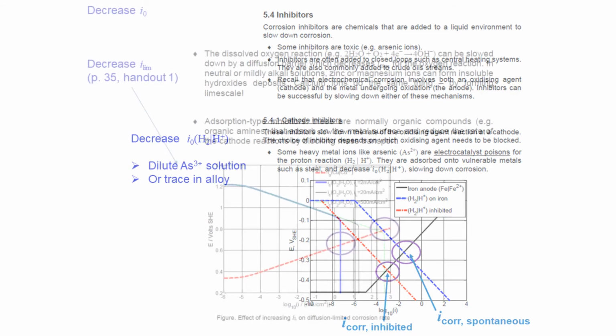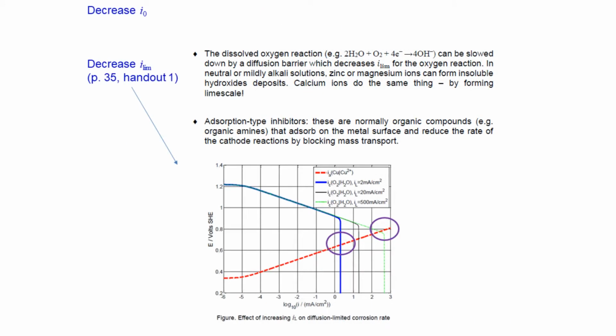We have a different kind of inhibitor to consider if our oxidizing agent is dissolved oxygen. This is because dissolved oxygen very often causes corrosion at a rate that is diffusion limited. So changing the exchange current density by decreasing it with some electrocatalyst poison often won't decrease the rate limiting step when corrosion is caused by dissolved oxygen, because the kinetics will still be sufficient to cause all of the oxygen reaching a metal surface to react and cause corrosion.